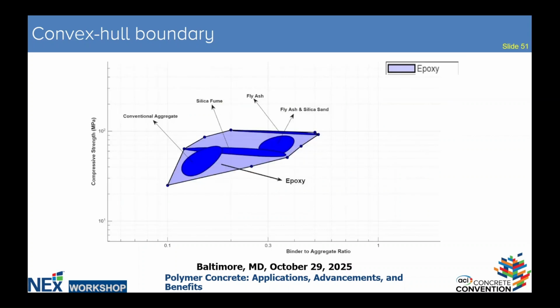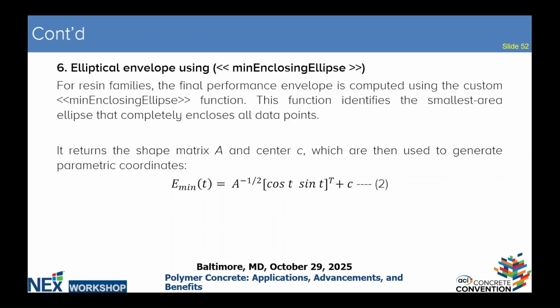So we have it here, which is the boundary type. And an Ashby chart is not a polygon, it's a bubble visualization. So with this polygon being drawn, or the contour being drawn around the epoxy, you're going to draw out a circumscribed ellipse to enclose this and just make the boundary disappear. The boundary gives us how the ellipse is going to hover around this data. So we use this equation, which is the minimum enclosing ellipse.